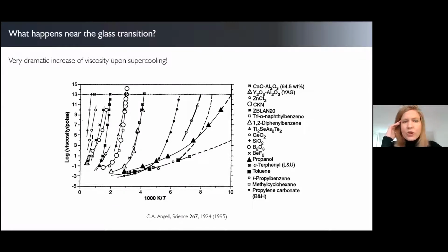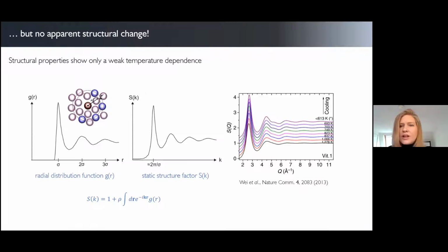And you see that for all these different materials, the viscosity shoots up by many, many orders of magnitude over only a relatively small change in temperature. So that's really a dramatic slowdown of the dynamics as you go from liquid to solid. However, if you then look at what happens with the structure of the material during glass formation, you will find that there is surprisingly almost no change happening in the structure of the material. And that makes it a very unusual phase transition in physics.